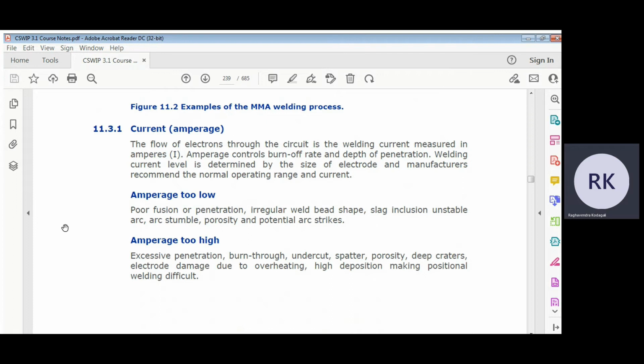So what will happen if it is too high? Excessively high current causes excessive penetration, burn through, undercut, spatter. These are typically new welder issues. When the welder is new or the machine is new, they are trying to adjust. Excessive penetration means the root will burn through and there will be a big hole in that, and then you will have to have a refit-up done.